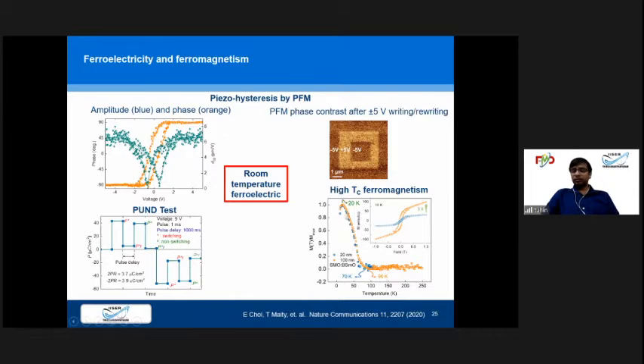And as well, when we measure the hysteresis loop, ideally it was an antiferromagnetic material. So in an antiferromagnetic material, the hysteresis loop is nearly like an S without any loop. But now we can see there is a loop here. So that means our sample has become ferromagnetic at the low temperature, but unfortunately it's still paramagnetic at the room temperature. So we have not yet achieved room temperature ferromagnetism. We are still working on it.